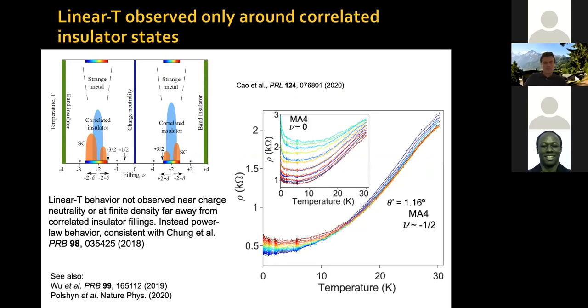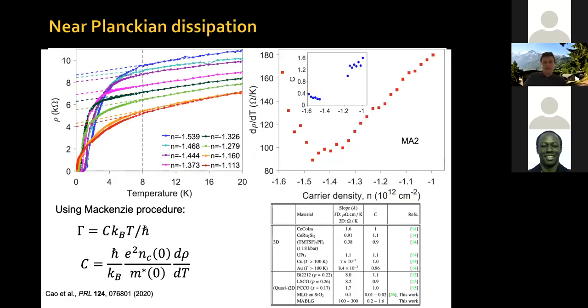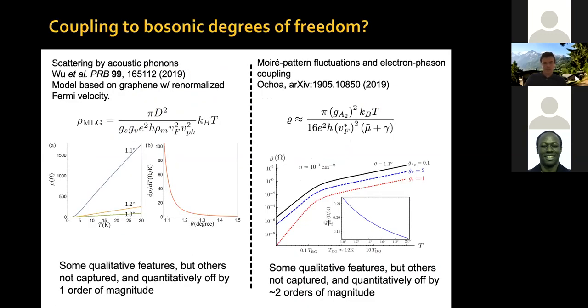Now, you can calculate the scattering rate for the system. For some samples, we're able to measure the scattering rate because we can do Shubnikov measurements and look at the temperature dependence. And then we see that this prefactor C is of order 1, between 0.3 and 1.5, okay? Which again means that this system seems to exhibit a linear T resistivity behavior with a close to Planckian dissipation scattering rate.